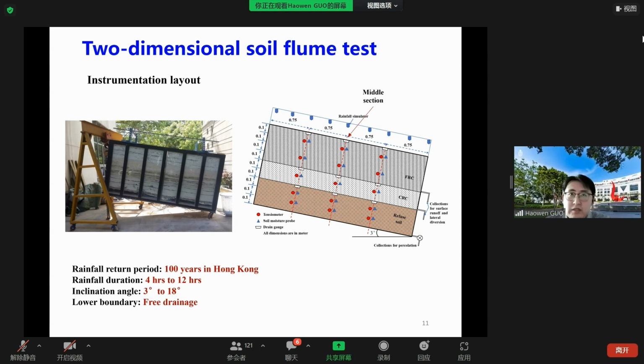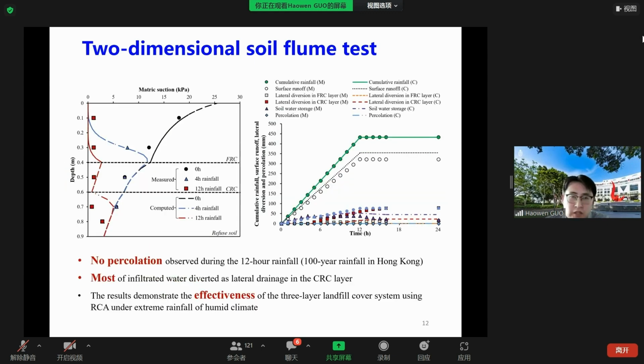So this slide shows the left-hand figure, which shows the comparison between the measured and computed soil suction profiles during the simulated rainfall. The total depth during the 12-hour rainfall was more than 400 millimeters. As the heavy rainfall was applied, the soil suction near the surface was the first to be influenced by the water infiltration, whereas the matrix suction in the middle CRC layer and the bottom layer was not changed after the end of the rainfall.